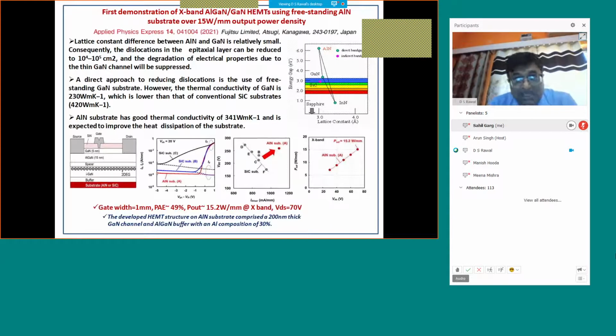And a lot of advancement is going on to improve the substrate properties also, and people are exploring other substrates for growing these HEMT structures, and zeroing in on aluminum nitride, because aluminum nitride is almost lattice matched to gallium nitride, if you can see here.